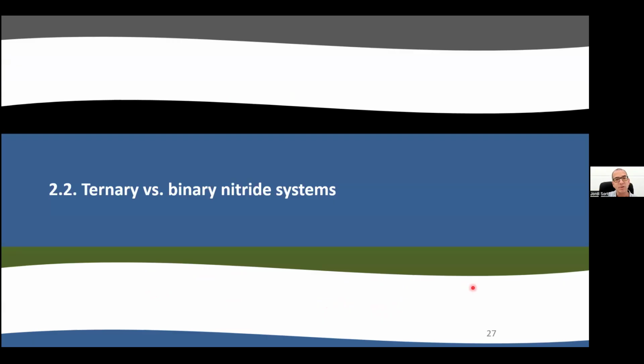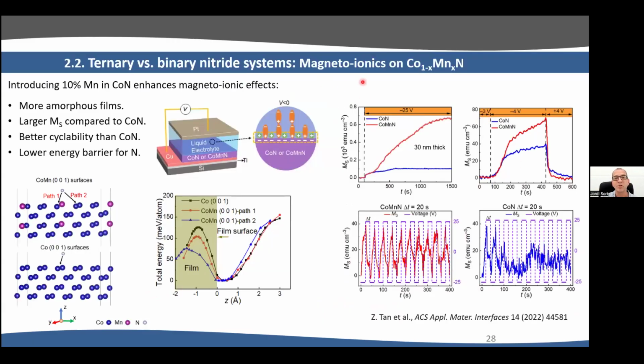Now, in the next slide, what I will show is that it's even possible to further improve the effects, moving from binary cobalt nitride to ternary compounds. Here we added manganese, for example. An addition of manganese into cobalt nitride makes the film more amorphous, and it improves the effect. So here I compare, again, cobalt nitride with cobalt manganese nitride. You can see that cobalt nitride has lower magneto-ionics than cobalt manganese nitride. And moreover, the cyclability, applying these 25 volts, is much better with cobalt manganese nitride than with cobalt nitride, where we lose the cyclability after 3 cycles.